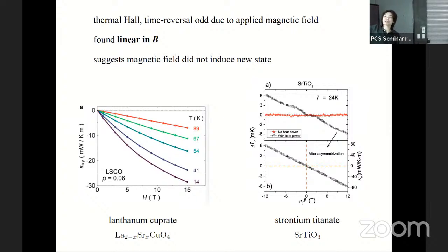Under the applied magnetic field, it is found that the thermal Hall effect is linear in the magnetic field. If something is linear in the magnetic field, then it seems there is no phase transition due to the magnetic field, right? If the thermal Hall effect is due to some phase transition or the magnetic field inducing some new state, then the effect usually should not be a linear response. So being linear in the magnetic field seems to suggest the phenomenon should be something relatively simple to understand, rather than some phase transition or whatever.